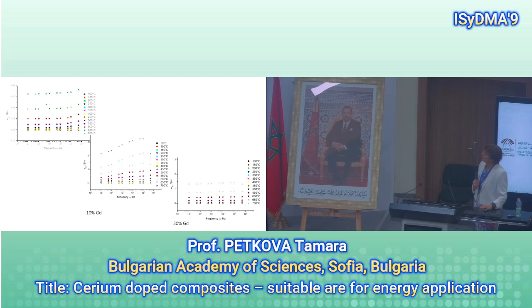From this experimental data, we calculated the conductivity of the materials, and the results show that with 10% gadolinium in the samples, we found orders of magnitude higher conductivity at temperatures of 650 and 700 degrees centigrade. It is interesting that with 30% gadolinium, we found that the values of conductivity decreased. Yes, I'm close to that.